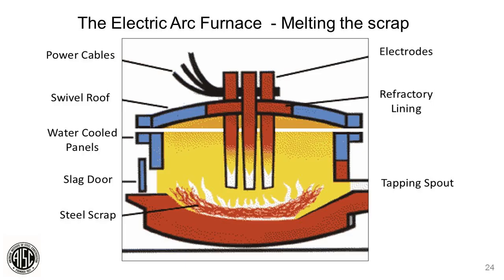So what is the electric arc furnace, and what are we talking about here? So this is a little diagram schematic of what an electric arc furnace is, and it has multiple components. What I like looking at is a big three-phase welder, and these big graphite electrodes conduct the arc plasma between all the 3 phases and create an incredible amount of energy and heat.